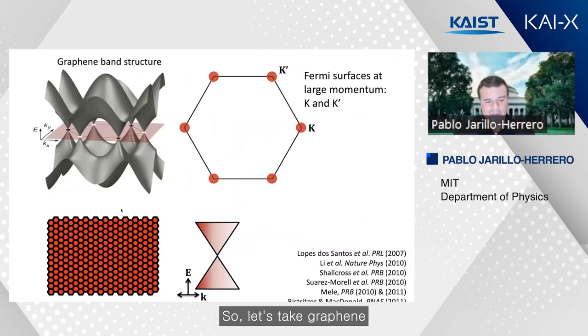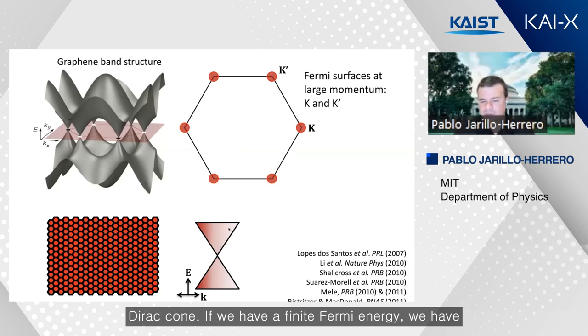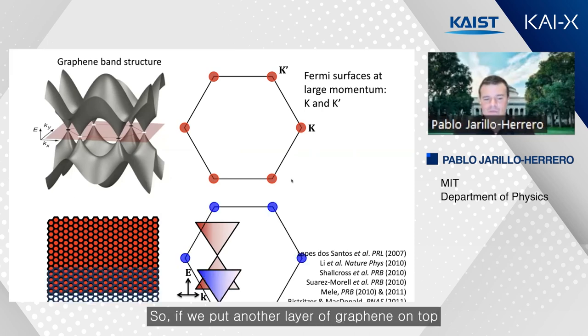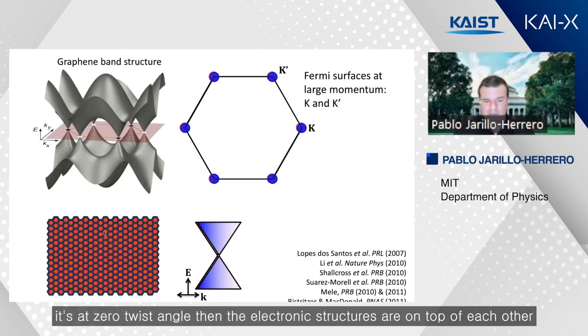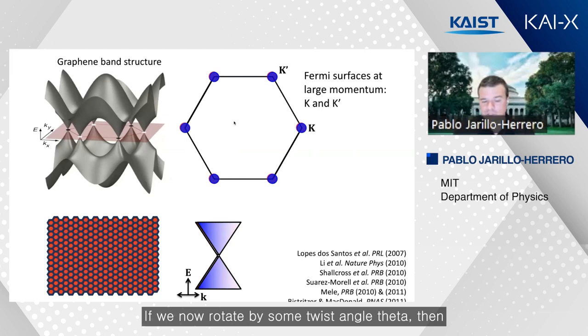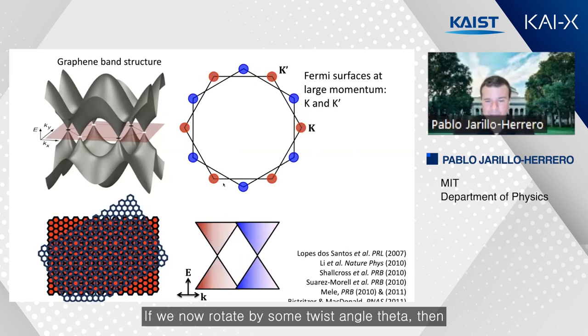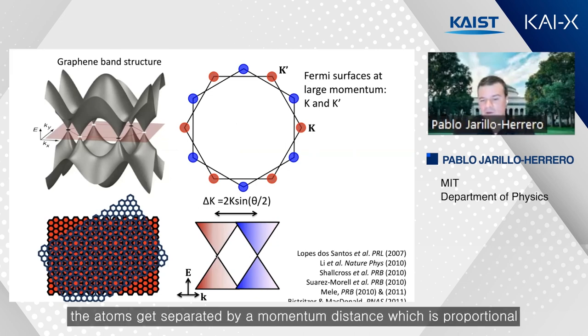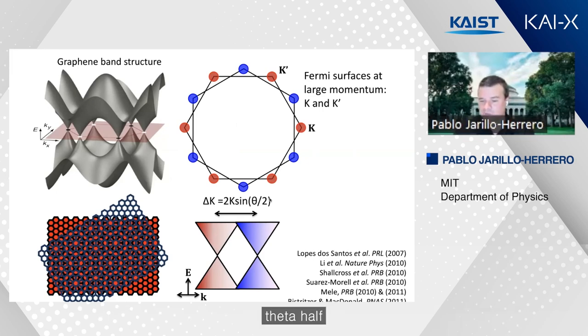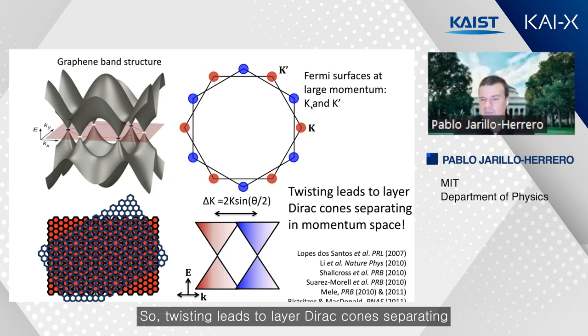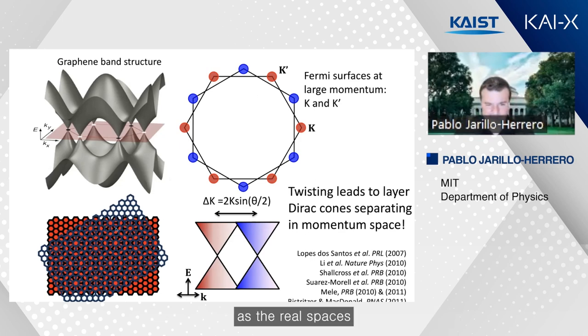So let's take graphene. This is the electronic structure, the Dirac cone. If we have a finite Fermi energy, the Fermi surfaces are these disks at the K and K prime points. If we put another layer of graphene on top at zero twist angle, then the electronic structures are on top of each other. If we now rotate by some twist angle theta, then the Dirac cones get separated by a momentum distance which is proportional to the sine of theta over two. So twisting leads to the layer Dirac cones separating in momentum space. The reciprocal spaces rotate by the same amount as the real spaces.